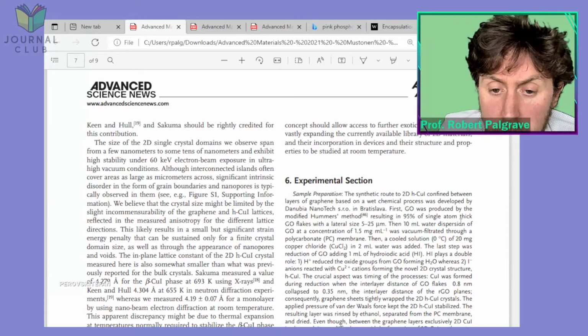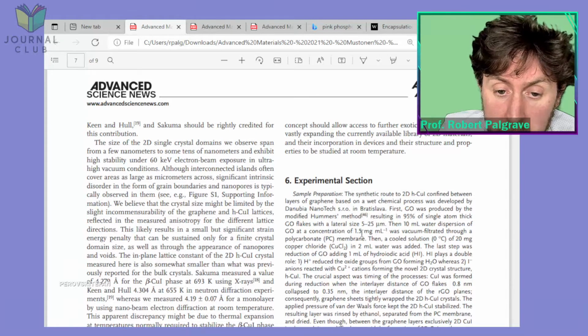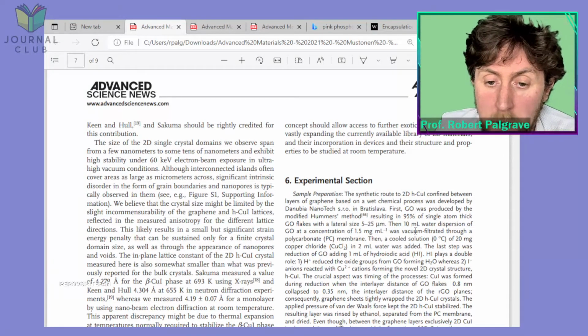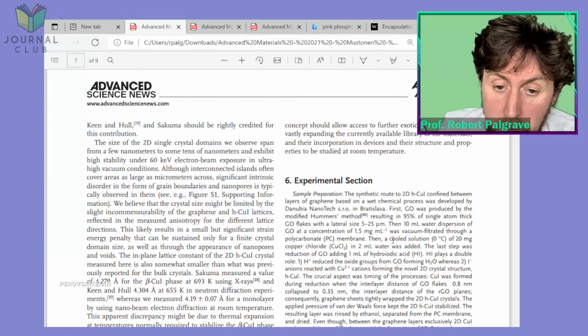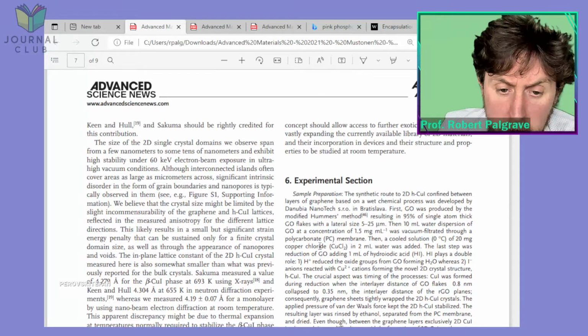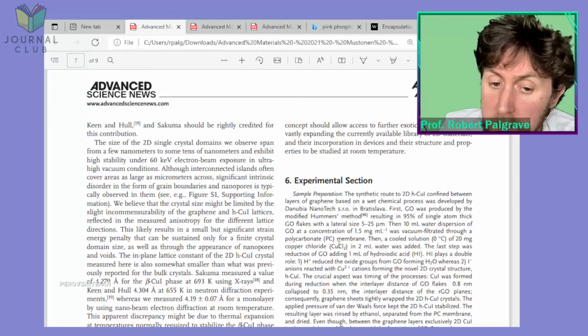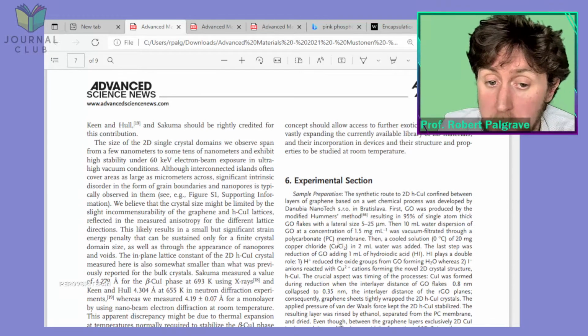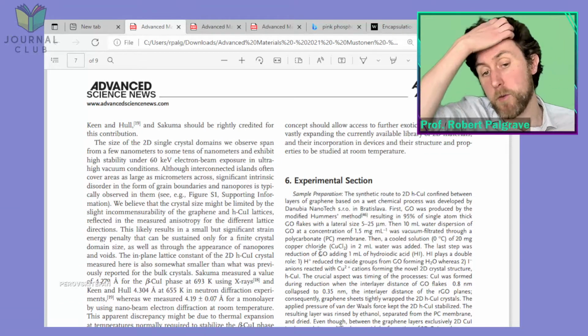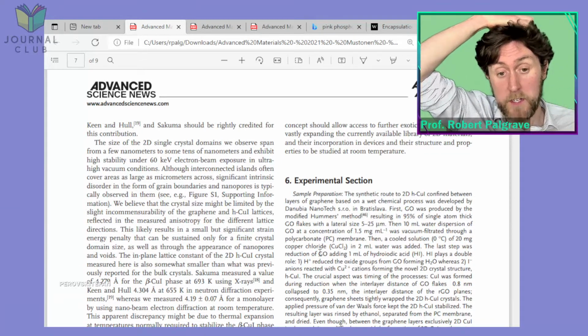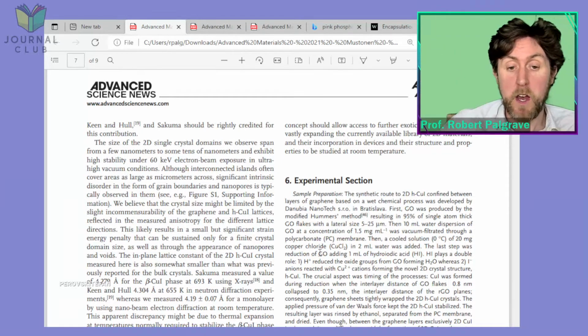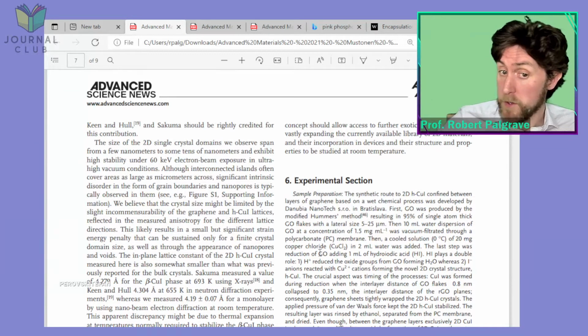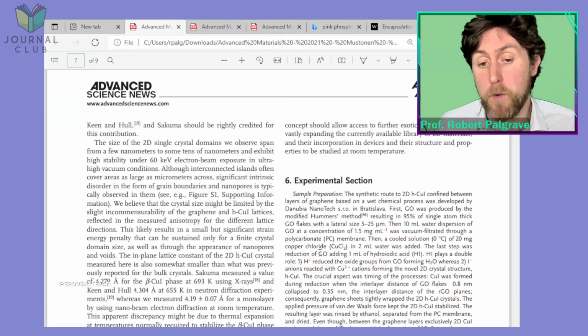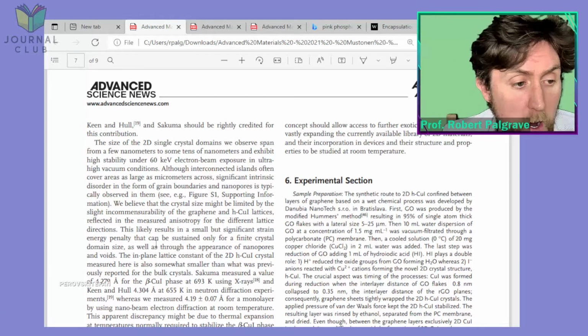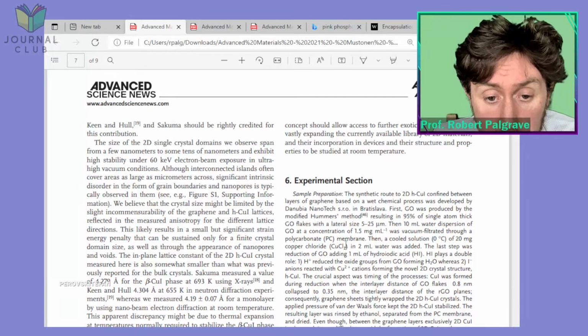10 mL of a water dispersion of graphene oxide at a concentration of 1.5 milligrams per milliliter was vacuum filtered through a polycarbonate membrane. A cooled solution at 0 degrees of 20 milligrams of copper chloride, CuCl2. Notice this is copper 2+ here. That's quite interesting. They're starting from a copper 2+ starting material. Obviously that's going to get reduced at some point, because the cuprous iodide that we end up with is copper 1+.